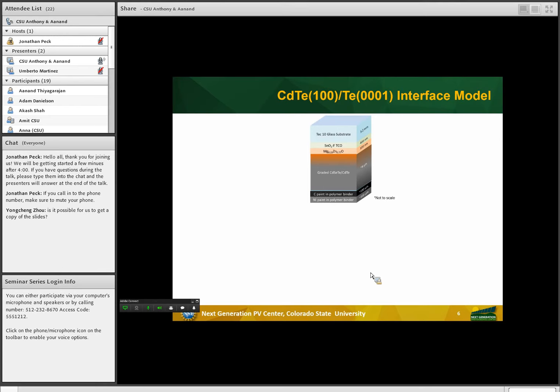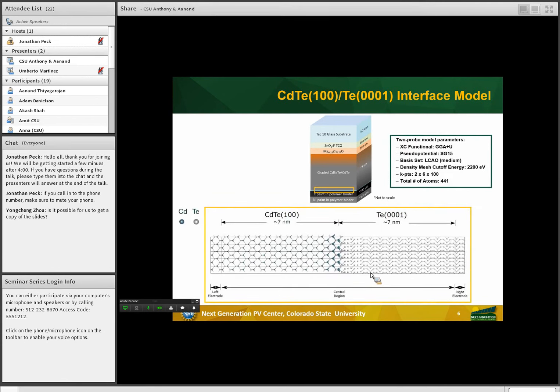The second model focuses on the CadTel 100 tellurium interface. We use a different CadTel plane compared to the previous model in order for us to determine how the grain orientation of CadTel affects the overall electronic properties of the device.